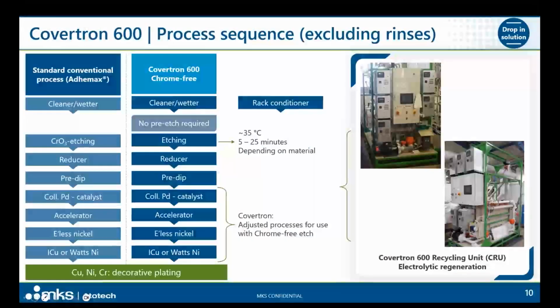The process sequence is also on the screen and allows, as you can see, a real drop-in solution, as there is not any pre-etch or any intermediate step required to go to the etching step, and it can work as well with any kind of pre-treatment, post-treatment that is after the electroless nickel. So whatever is currently in the plating line, be it immersion copper, nickel strike, or copper strike, can work with Covertron 600. So this is what we say is really a one-to-one replacement for the sulfur-chromic etching process as we know it today.